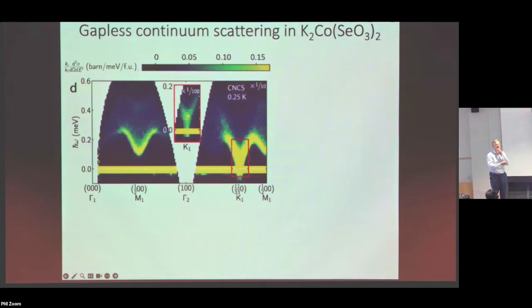So it's pretty difficult to get. It's not impossible. IN5 at ILL has very good resolution as well. But this machine gets down to about 15 micro-electronvolt resolution. And we have another machine, or they have another machine that goes to 3 micro-electronvolt, which is really spectacular. It's pretty difficult to do. Not impossible, but you can't do it with this level of intensity, I would say.